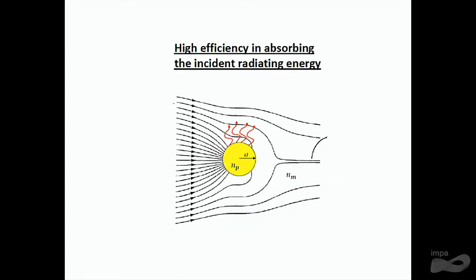So you put the particle, you intercept a fraction of the light that is incident into the detector that is proportional to the cross-sectional area of the particle. If you remove it, all the light goes to the detector. What happens when you have a gold nanoparticle? A gold nanoparticle has particular characteristics that make the light that goes to the particle be taken by the particle in a larger amount than its cross-sectional area. So it takes more light than is normal for a regular particle to take.